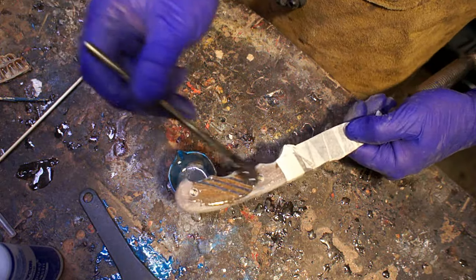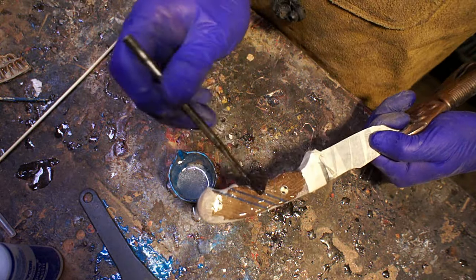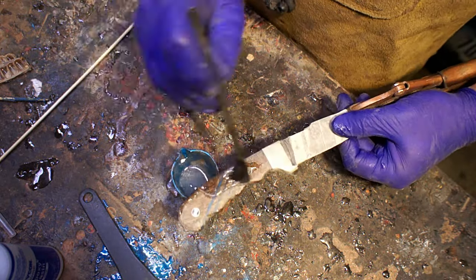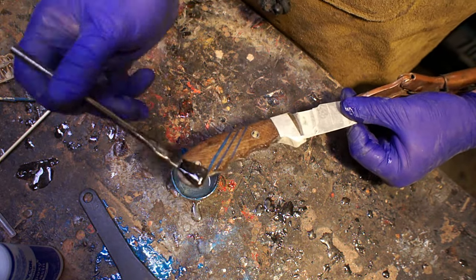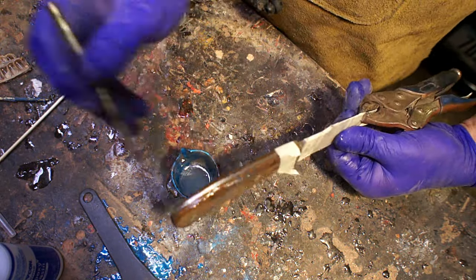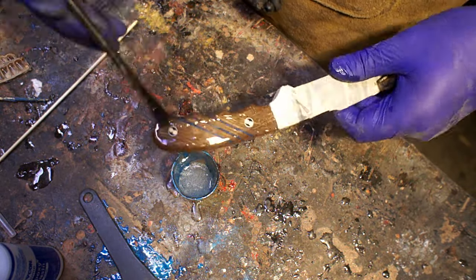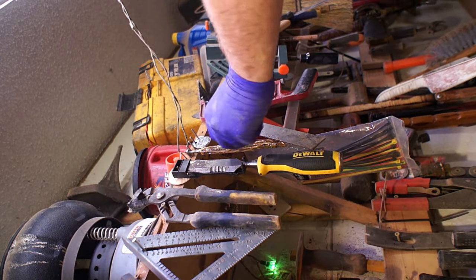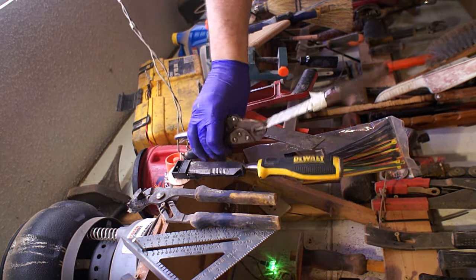With the final shaping done I noticed a couple little pinholes — just where the epoxy didn't penetrate all the way when I was laminating. So I went back in and did another skim coat of the same epoxy resin just to fill everything in. After that cured I sanded everything smooth again, all the way up to about 220 grit before applying the clear.